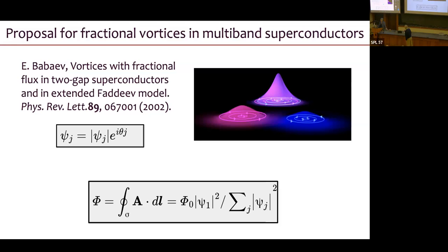Yes, I agree. So the question is whether spatial anisotropy is expected or has been seen in the vortices of a superconductor with nodes. And there have been BCS-based naive expectations of starfish-shaped vortices in cuprates. And actually, you can get starfish-shaped vortices just from the band structure. So one of the most famous early imaging of vortices was done by Harold Hess at Bell Labs using scanning tunneling microscopy. He was also the first person to use a scanning Hall probe to magnetically image a vortex, by a technique that wasn't Bitter decoration.